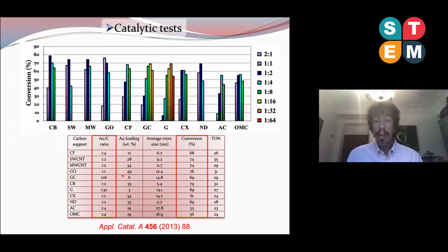And by adjusting the gold carbon ratio for all these materials, we got successful results in terms of conversion, or catalytic activity, for the hydroamination reaction. In particular, it worked pretty well for graphene oxide and for all materials with high surface area and good dispersibility in water and well-developed mesoporosity.